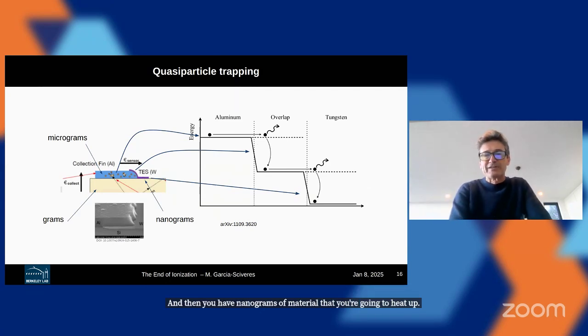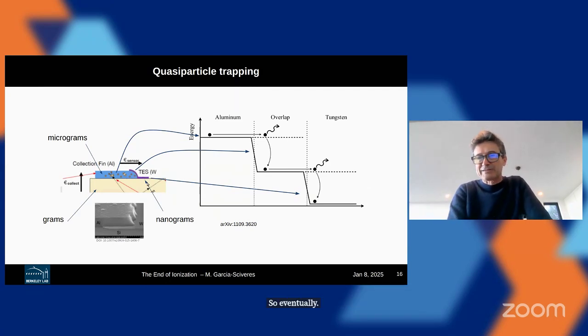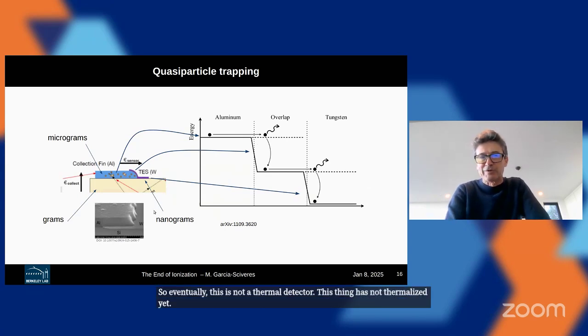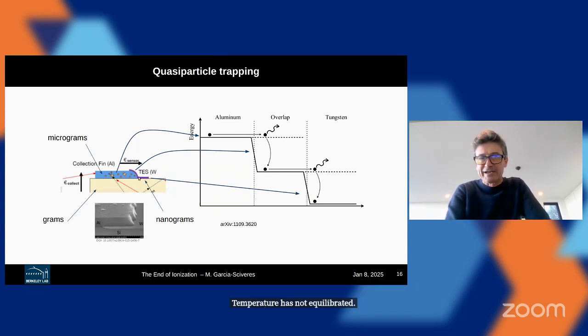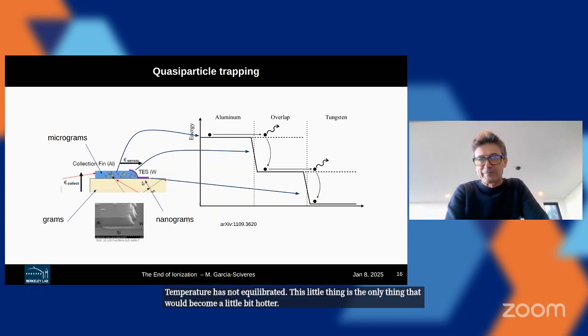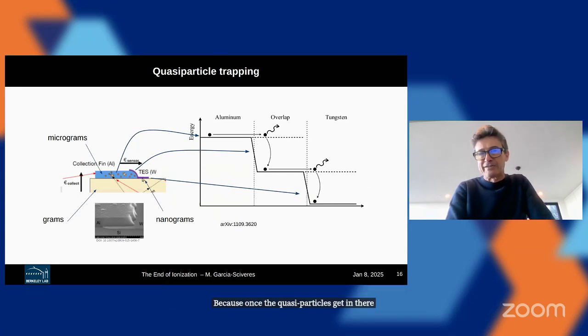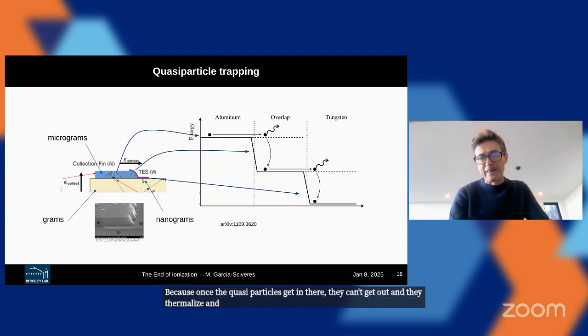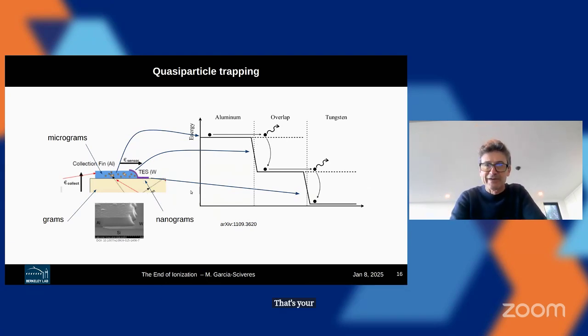So eventually, this is not a thermal detector. This thing has not thermalized yet. The temperature has not equilibrated. This little thing is the only thing that became a little bit hotter, because once the quasi-particles get in there, they can't get out and they thermalize and they raise the temperature. That's your TES. So this is a very nice method.